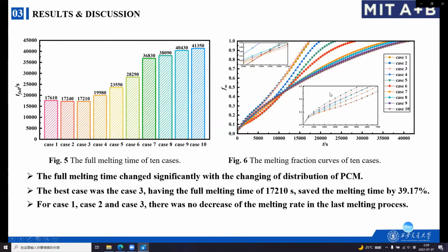that the melting fraction curves of the 10 cases coincided before about 500 seconds. This was mainly because at the beginning of the melting, only the PCM near the copper tube was heated up by conduction and melted. Therefore, the different distribution of PCM had no effect on the melting of PCM. So the melting fraction of each case was almost the same. So the curves coincided.